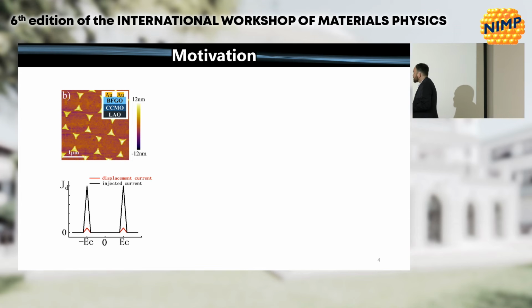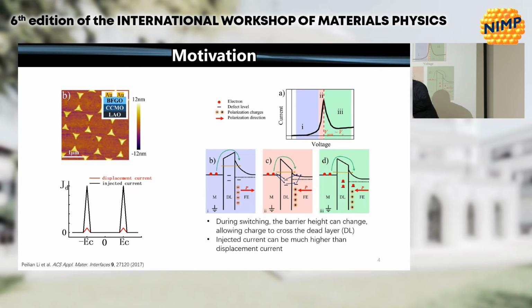Here's another example. So in this work by Peilian Li, you can see that we have this displacement current, the switching current, but on top of that we have an injected current that happens during the switching. And they discuss that in terms of tunneling through the dead layer, basically. So during switching, the barrier height can change. We have some interfacial layer, and as you're switching, you can get charge to be injected across, and that can lead to an enhancement orders of magnitude higher than the displacement current. And so maybe that could be used for the detection of whether or not your domain is switched in your ferroelectric memory device.